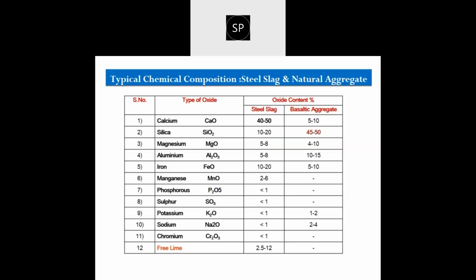Now, that's all on the front of the chemical composition of the aggregate. In terms of the specific gravity, the steel slag aggregate is around 30 to 40% heavier than the natural aggregate. The good quality natural aggregate is between 2.78 to 2.83, while the steel slag aggregate is between 3.1 to 3.5. Up to that much variation can be seen in the specific gravity, depending upon the quantity of metallic iron going along in the slag. So if there is high metallic iron entrapment, then the specific gravity of the slag will be higher, which can be reduced by removing the entrapped metal through the magnetic separation process.